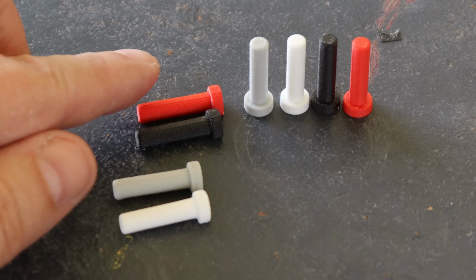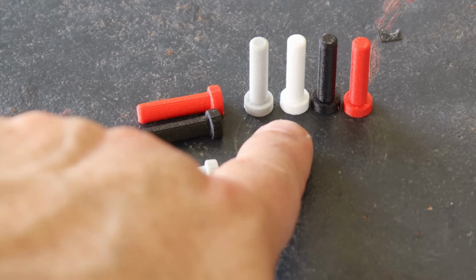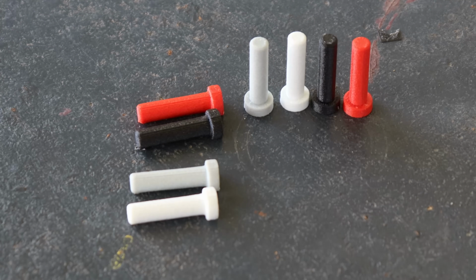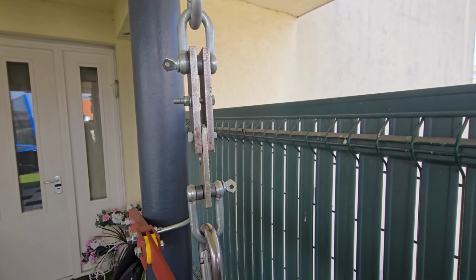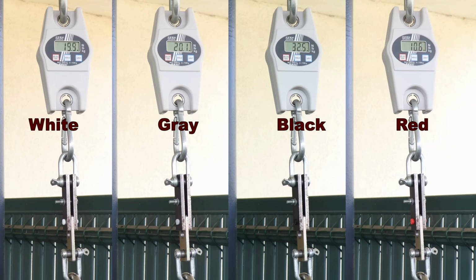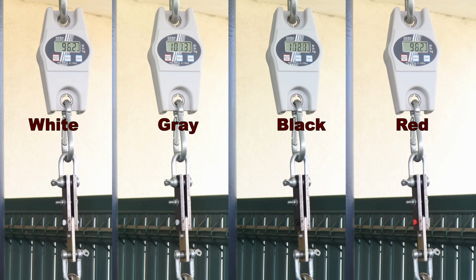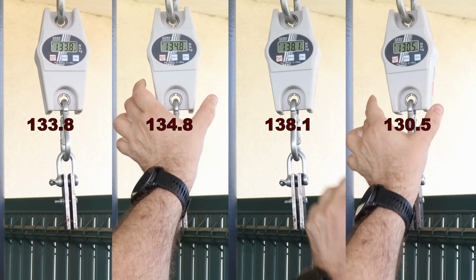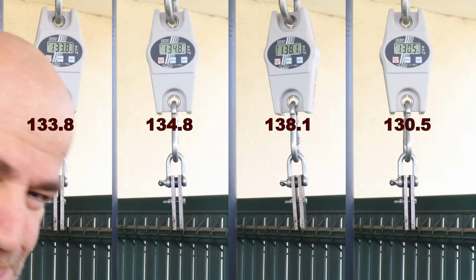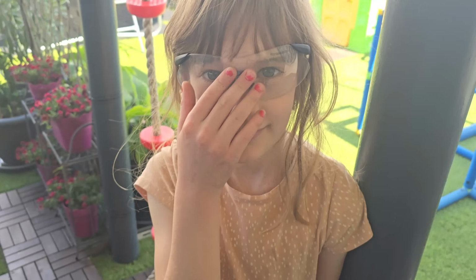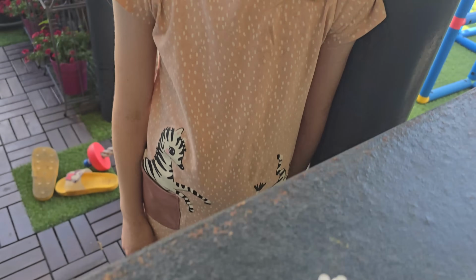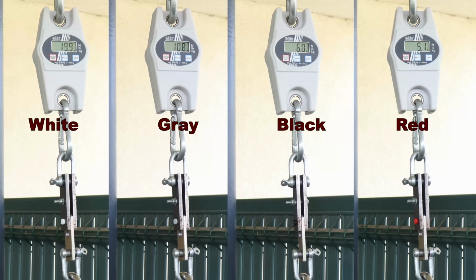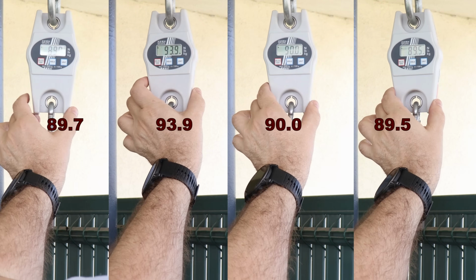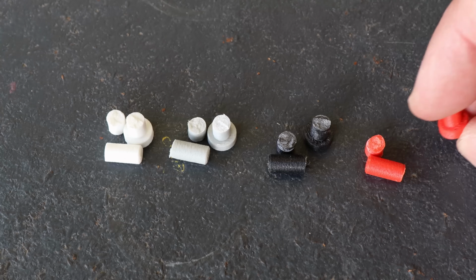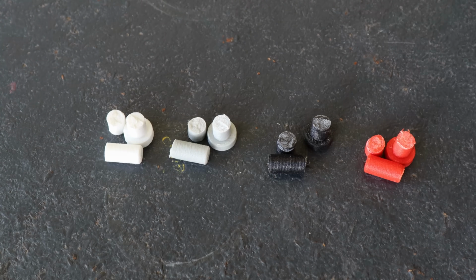The shear test, diameter 5 mm, and beside this horizontally, first time I have these vertically printed test objects too. Here you can see my test equipment. Side by side, all four, these are horizontally printed. Very strong in all four cases. The glass fibers really help their orientation. And thanks to my helper, I could find all flyaway parts too. And now these are printed in vertical position, so the layer adhesion is very important here. And I was quite surprised, so 90 kilograms, this is quite strong for this test.